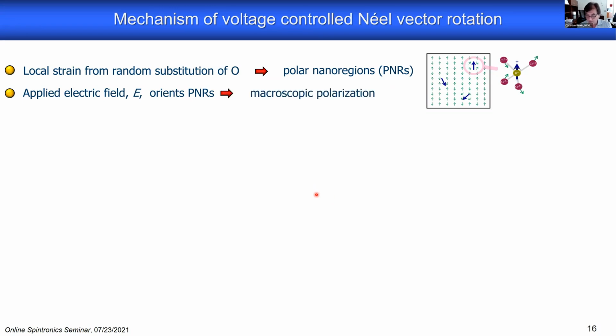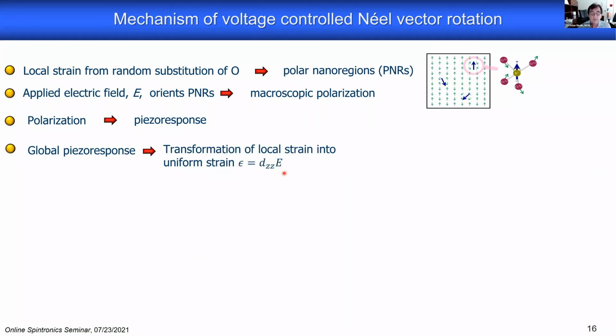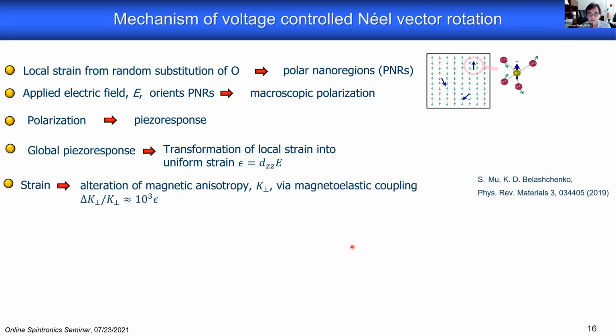Now, this macroscopic polarization has a piezoelectric effect. It creates a piezoelectric response, epsilon, delta L over L, which is given by d_zz times E, the electric field. And this piezoelectric response creates a strain, and this strain affects the magnetic anisotropy. Why am I confident that the strain affects the magnetic anisotropy? Well, there is again extensive work done by Kirill Belashchenko's group on exactly that, namely how strain affects anisotropy in pure chromia.